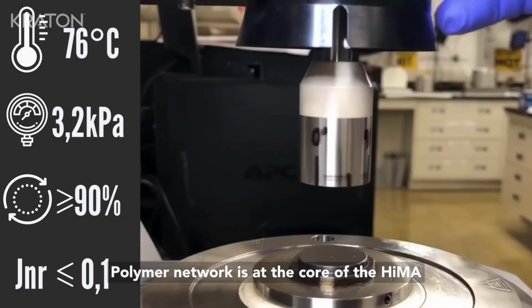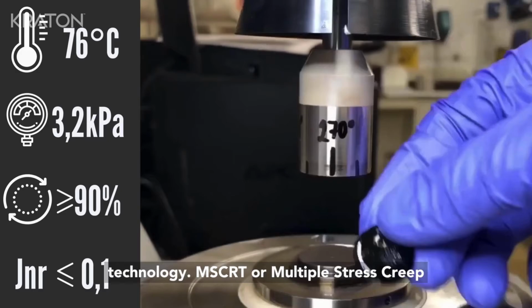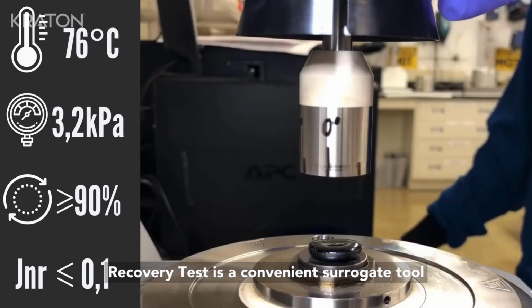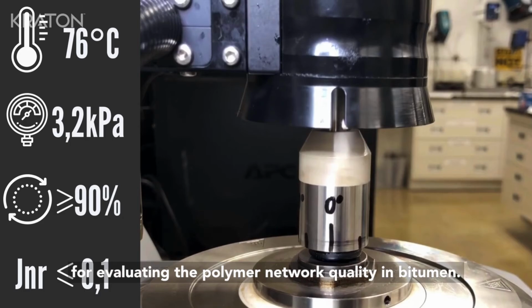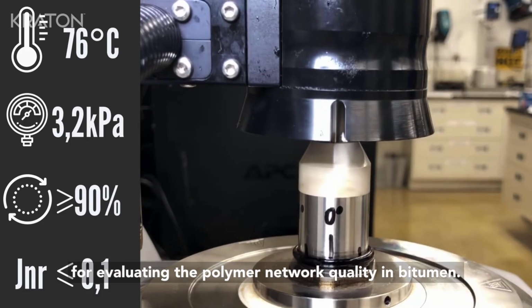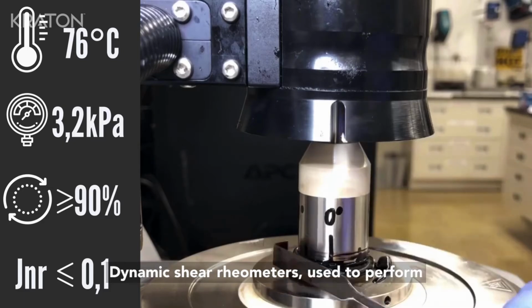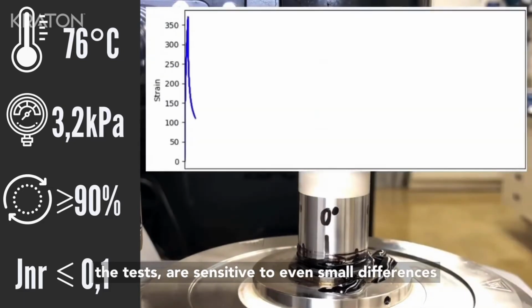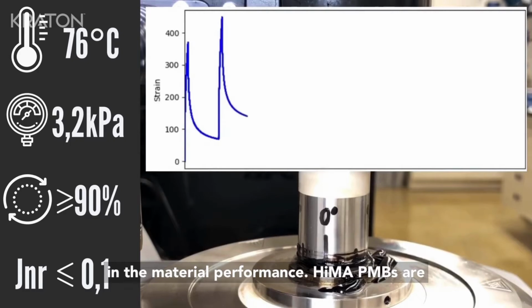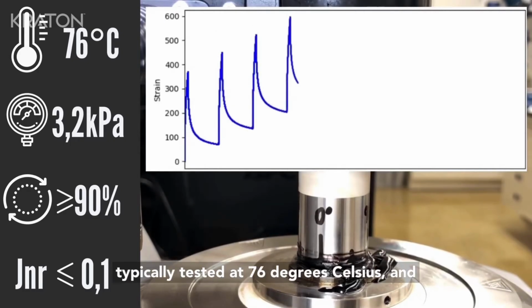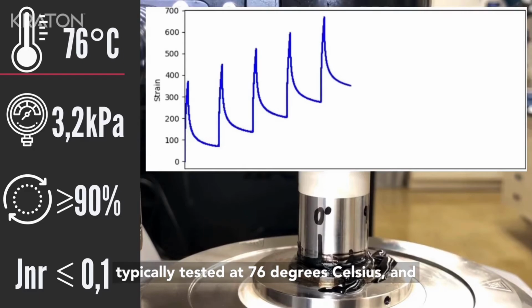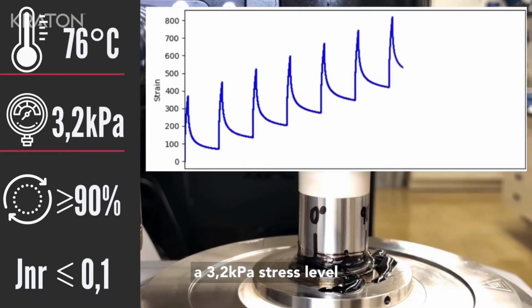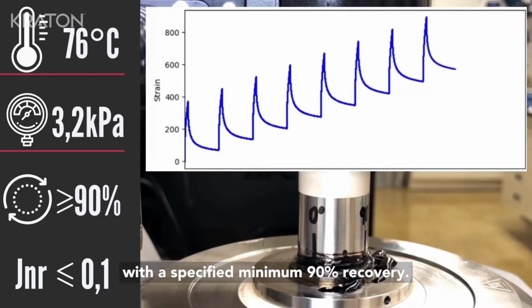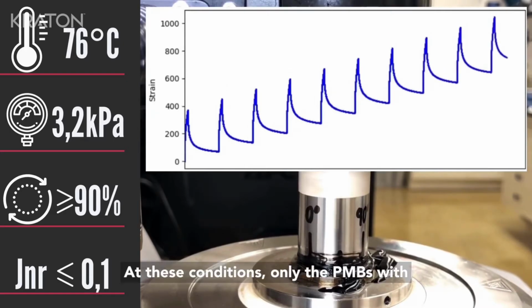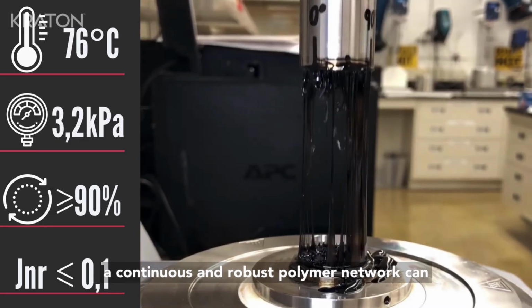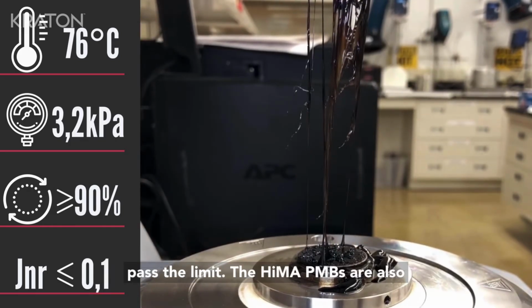Polymer network is at the core of the HiMA technology. MSCRT, or Multiple Stress Creep Recovery Test, is a convenient surrogate tool for evaluating the polymer network quality in bitumen. Dynamic shear rheometers used to perform the test are sensitive to even small differences in the material performance. HiMA PMBs are typically tested at 76 degrees Celsius and a 3.2 kilopascal stress level, with a specified minimum 90% recovery. At these conditions, only the PMBs with a continuous and robust polymer network can pass the limit.